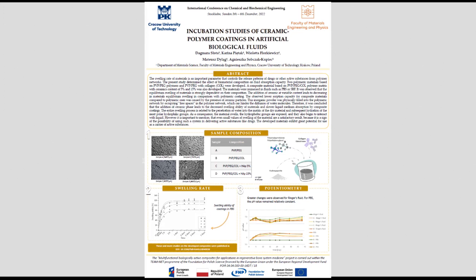The next investigation was to determine the sorption capacity, because the material that swells can potentially be used as a carrier for an active substance. So that was a really important parameter for us to detect. The highest sorption capacity was observed for polymeric materials, especially for sample B, the sample containing additionally collagen. And for composites, the value decreased as the proportion of the ceramic phase in the biomaterial increased, because hydroxyapatite grains occupied the free spaces between the polymer chains, thus reducing the liquid absorption capacity.